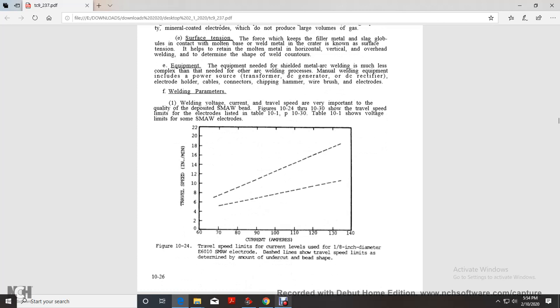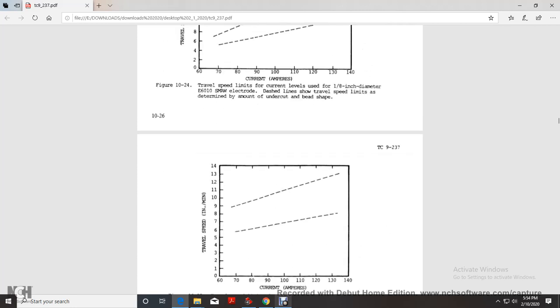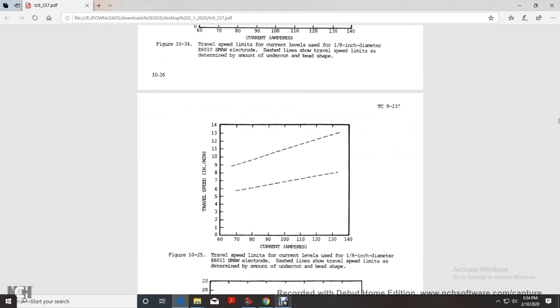So in Figure 10.24, you have the travel speed with the current level for a 1/8 inch diameter E6010 shield metal arc welding electrode. The dash line shows the travel speed limited by the determined amount of undercut and bead shape. Travel speed in inches, then current in amperes. Then you have travel speed and current in amperes for a 1/8 inch diameter E6011. The dash line shows the travel speed limits that determine the amount of undercut and bead shape.